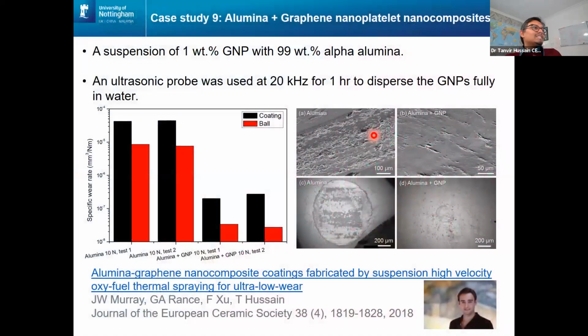Here, this is the first time we worked with some cheap graphene particulates. We call these graphene nanoplatelets. So these are not single layer pristine graphene. These are 5 to 6 atomic layers thick, very cheap graphene nanoplatelets. And we are adding 1 weight% with alumina, which was our base coating. And here you can see we rubbed an alumina ball against the coating without the graphene nanoplatelets. You can see how deep the scar is, and you can see the scar on the counter body, which is the ball.